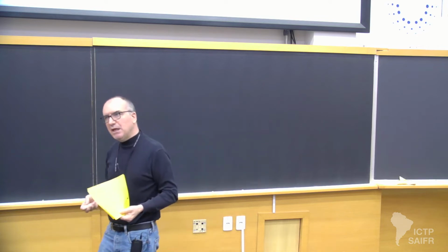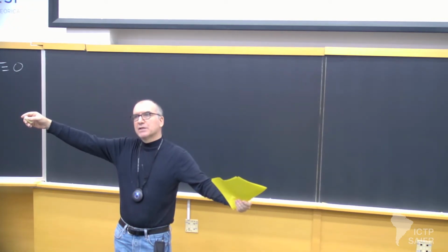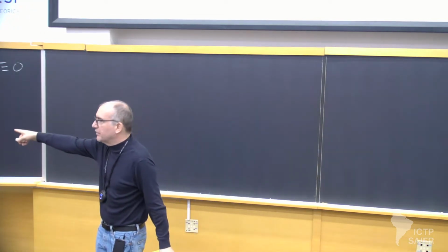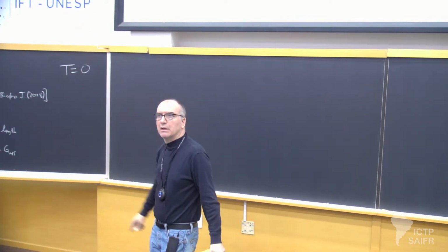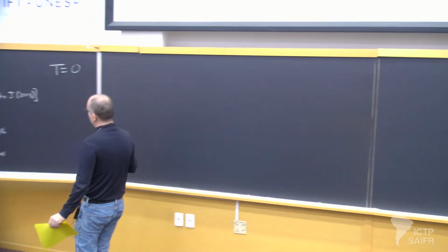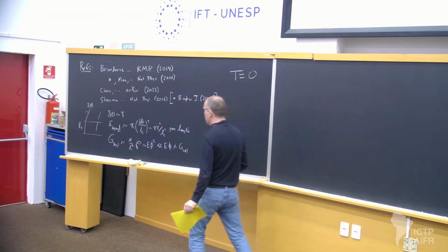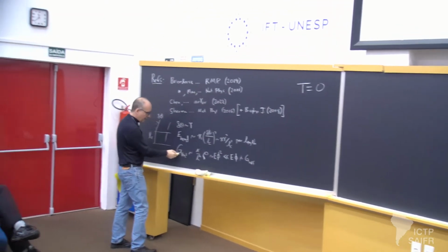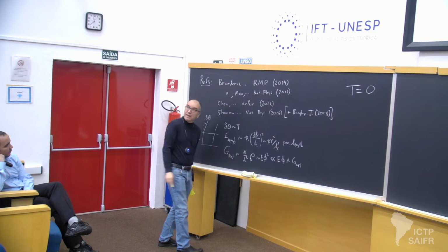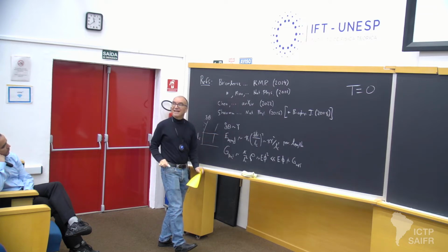And what that tends to mean is that those fibers can have very long-range mechanical effects that go well beyond the scale of the mesh, or an approximate unit cell size, let's say. And here's the problem that occurs in this affine limit. It's important to note this modulus, through this argument, depends on the bending rigidity of fibers. Stretch modulus doesn't appear. That literally means this deformation mode doesn't generate any stretching at all. OK, so nothing's getting stretched.